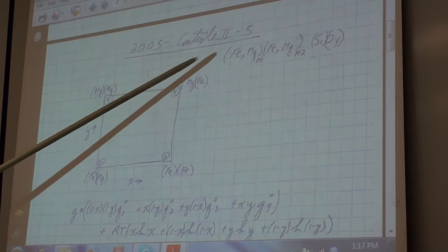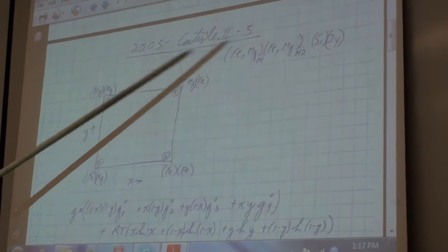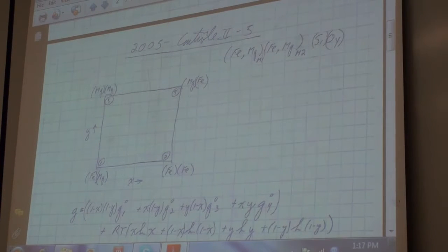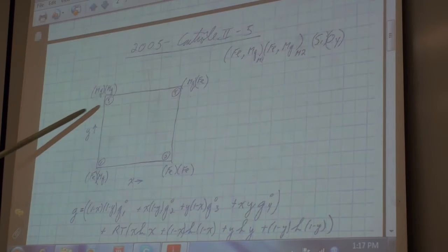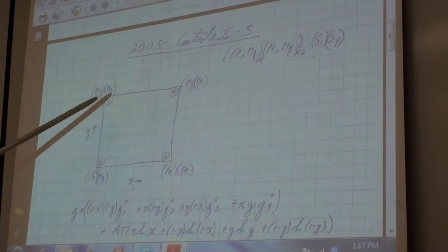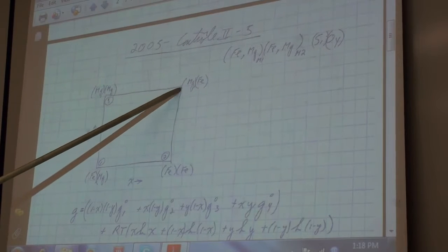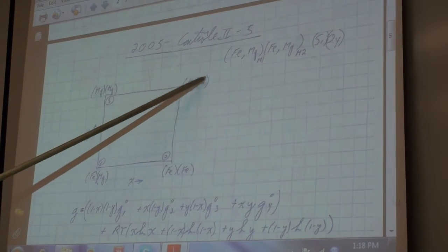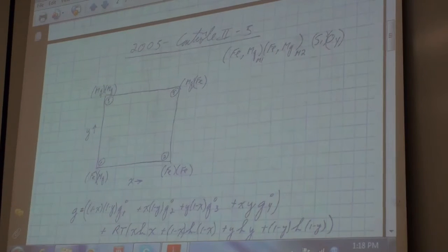The M1 and M2 sites have different energies on them, and basically the iron prefers one site and the magnesium prefers the other site. So one of these, 1 or 4, is going to be favored over the other. If you go from pure Mg2SiO4 to pure Fe2SiO4 through the system at internal equilibrium, if the 2 sites had the same energies, then your composition path would be a straight line along the diagonal.